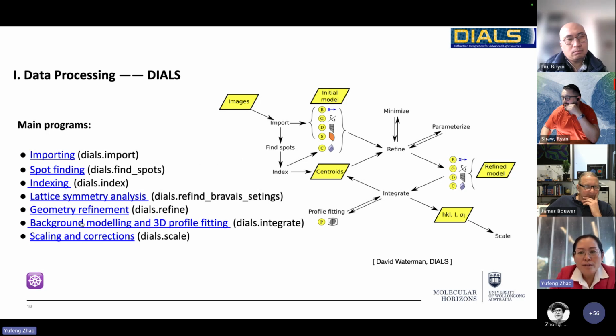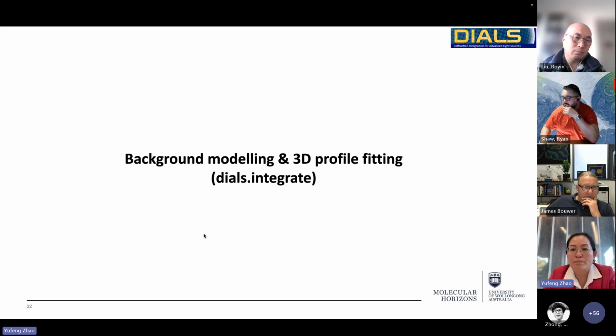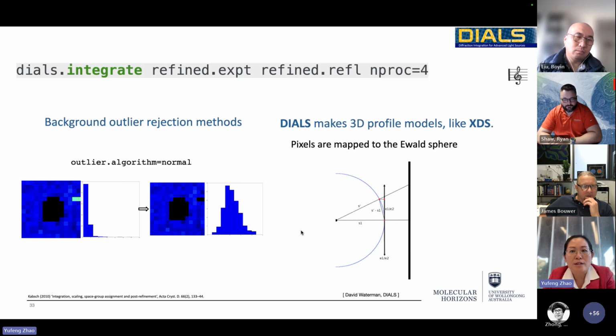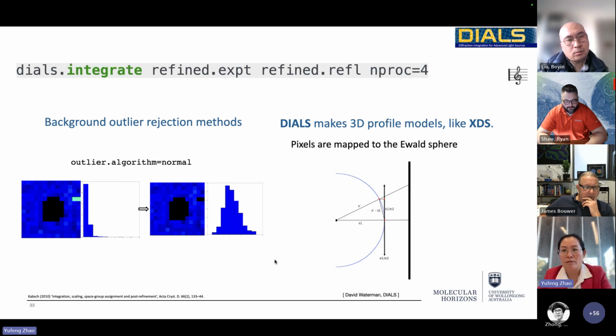Then after finishing all this geometry refinement, we would like to build up the final model. It does 3D profile fitting to get this model, similar to XDS on this bit. So the pixels are mapped to the Ewald sphere by the 3D profile fitting process. And the pixels are analyzed by a background outlier rejection method. So finally we get a normal distribution. So it's quite reliable.